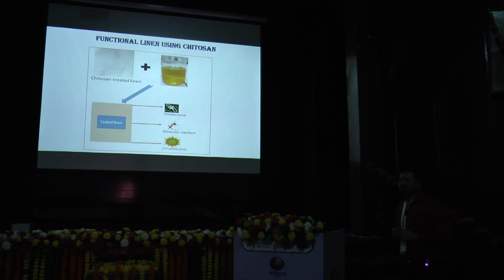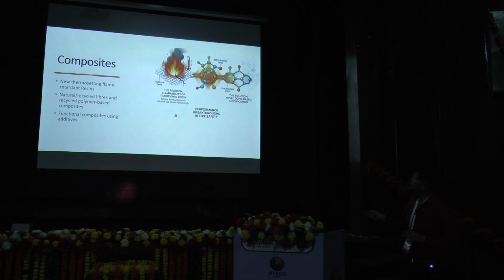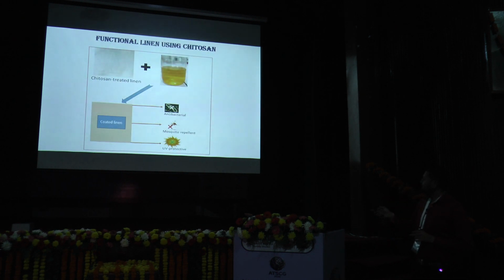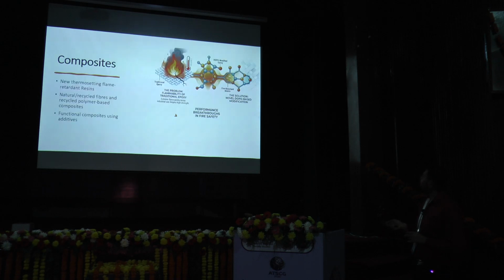So then we have chitosan, which is a very important polymer. We use chitosan to make a coated kind of linen, and this coated linen is mosquito repellent, antibacterial and UV protected. Very simple process. You have to treat the cellulosic fabric with this, and this is treated with chitosan. You will end up with all these properties. Very quick process. This is also patented.